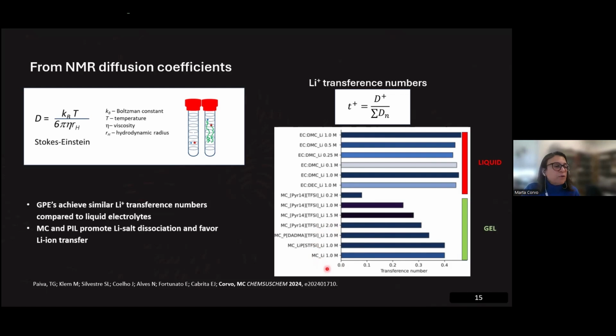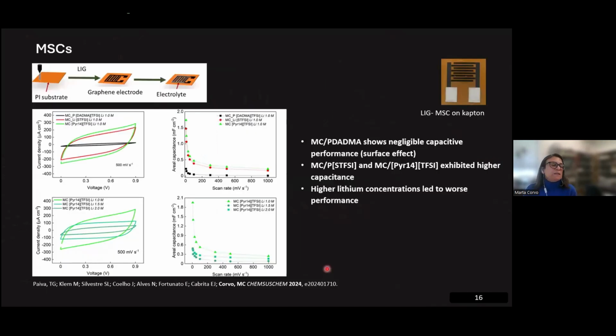What we did next was to use these gel polymer electrolytes in micro supercapacitors that were generated on these Kapton substrates. These graphene electrodes were produced in the Kapton with laser-induced graphene. Graphene is quite interesting to use because it's highly porous, and it's right there in the substrate. We made these devices like this and deposited the gels in them, and then started to look at the behavior, the performance of these micro supercapacitors.